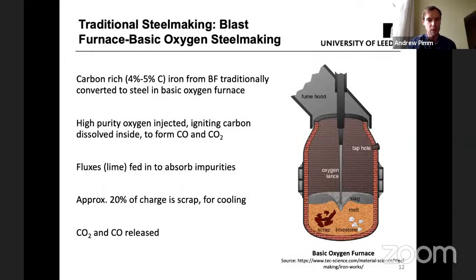You get hot metal out, which is effectively pure iron or carbon-rich iron. So you then need to reduce the level of carbon down to a small percentage to give you steel. And this is done at large scale using the basic oxygen furnace. High purity oxygen is injected into the liquid iron. This ignites the carbon which is dissolved in there, forming carbon monoxide and carbon dioxide. So again, more carbon dioxide emissions. Lime is used to absorb impurities, forming slag, which is removed. Scrap is also inserted in there, approximately a 20% charge of scrap, used for cooling. And yeah, as I said, CO2 and carbon monoxide are released in that process.